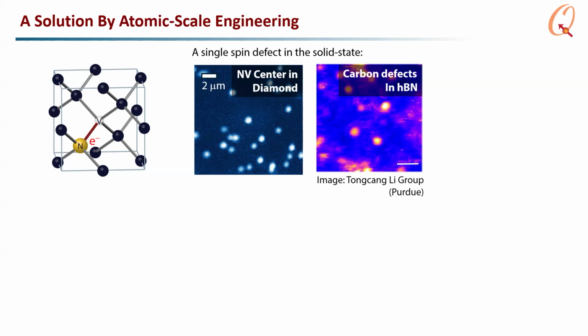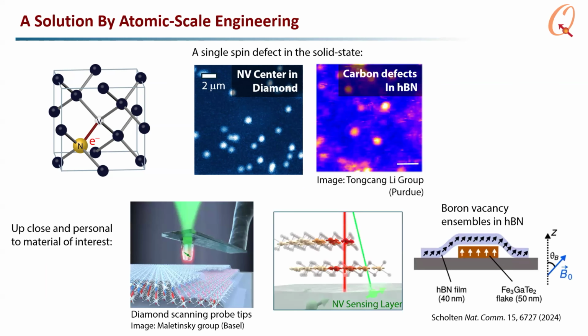the recent creation of single defect centers in the solid state. So for example, the nitrogen vacancy center in diamond is a substitutional nitrogen next to a vacancy, and we can isolate the fluorescence of single NV centers in the lattice, as well as now there are single carbon defects that you can isolate in hexagonal boron nitride. And what's great about these single spin defects is that you can get very close to materials because they are trapped in the solid state.